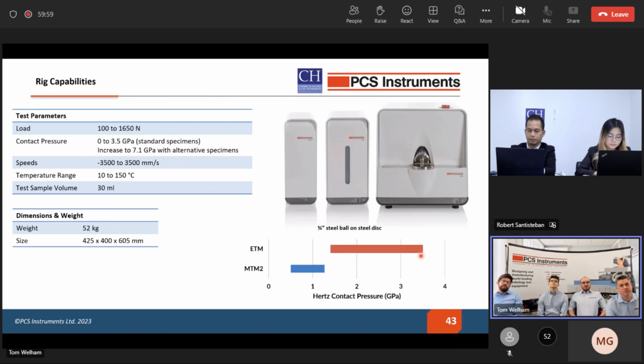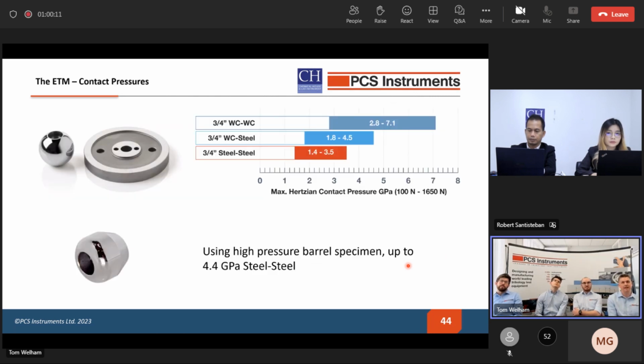So up to 3.5 gigapascals with the same geometry specimens as with the MTM2. And this shows the contact pressure range we're able to test under. Otherwise, the spec is very similar. A little bit more about contact pressures with the standard specimens, as I say, up to 3.5 gigapascals. But we can use tungsten carbide specimens if we want to go even higher. Contact pressures as much as 7.1 gigapascals, so extremely high. Or if we want to stick with steel, we can change the geometry of the ball to give a sharper radius, which increases contact pressure, and that will take us up to 4.4 gigapascals, still with a steel contact.